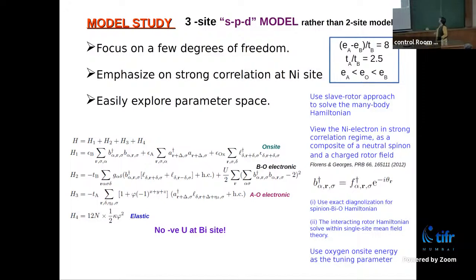And we did some model study. Now it's not a bismuth-nickel model, it's a 3-site model. We need to involve bismuth, nickel as well as oxygen, because oxygen is our main player. So we have basically 4 parts of this Hamiltonian. You can just write it very easily. These are the on-site energies of bismuth, nickel, and oxygen. These are the hopping integrals, bismuth-oxygen, nickel-oxygen. In this case, nickel being a strongly correlated electron system, I have to put some U term, and that U term is shown here. In case of the bismuth, I do not have such a strong thing, but I do have this restoring force, because if this lattice is trying to contract and expand, there should be an elastic energy cost, and that is what is shown here. We note there is no negative U at the bismuth site, because that was our goal. And then we basically solved this problem with the slave rotor approach.